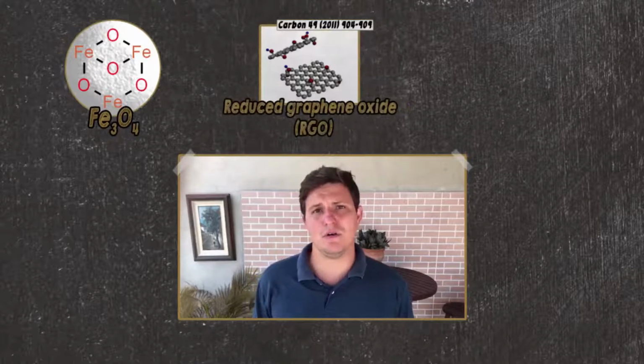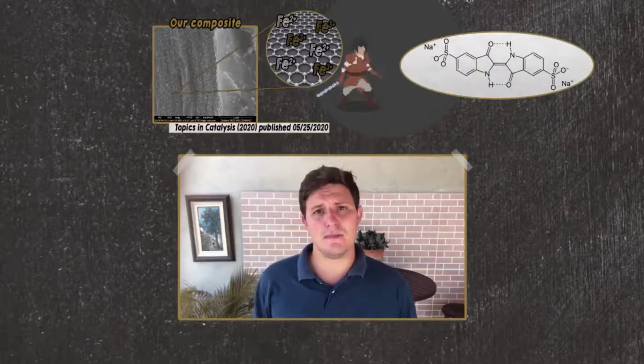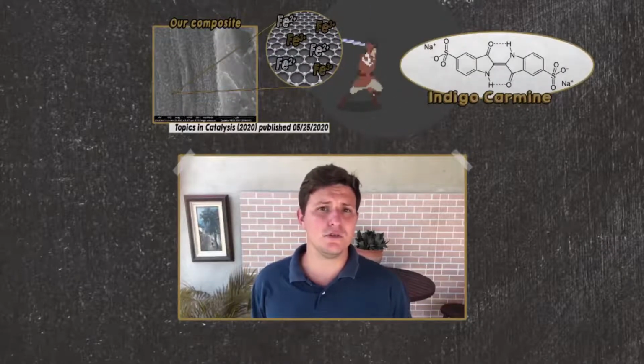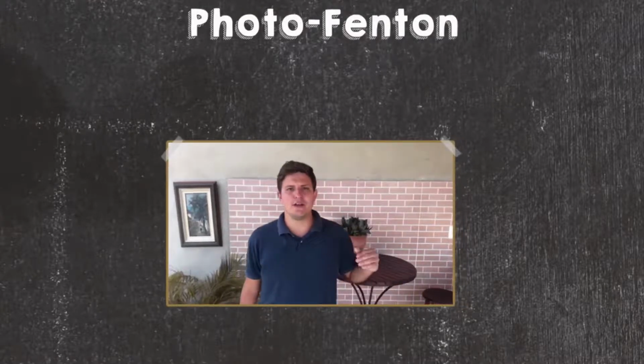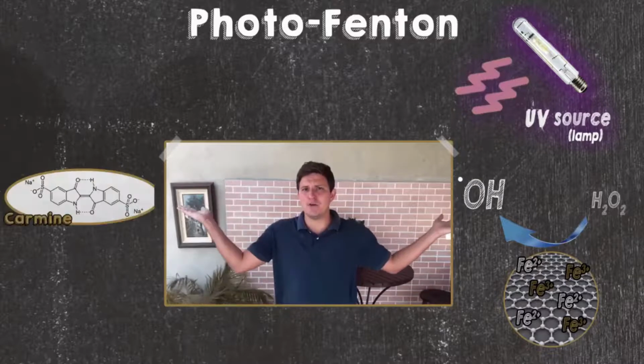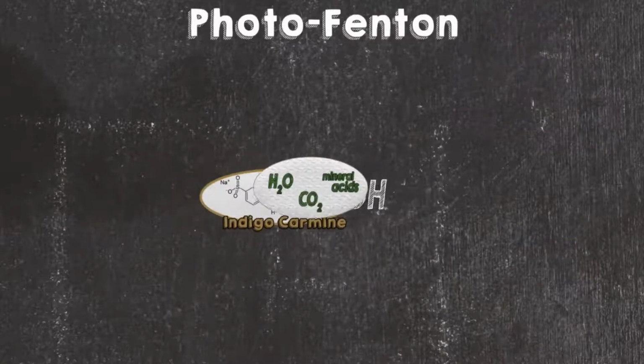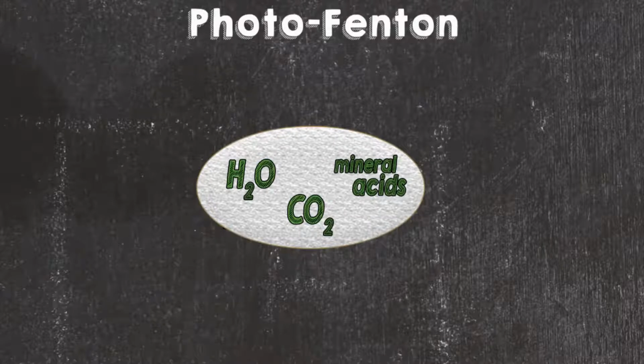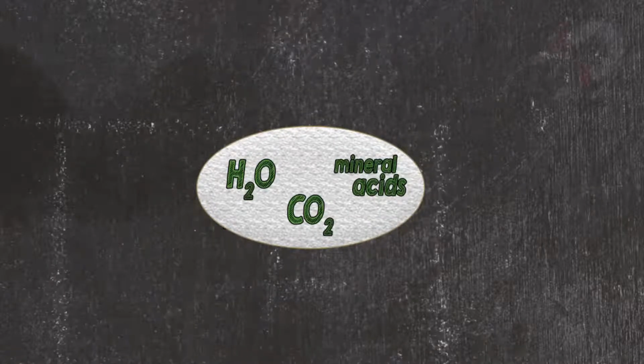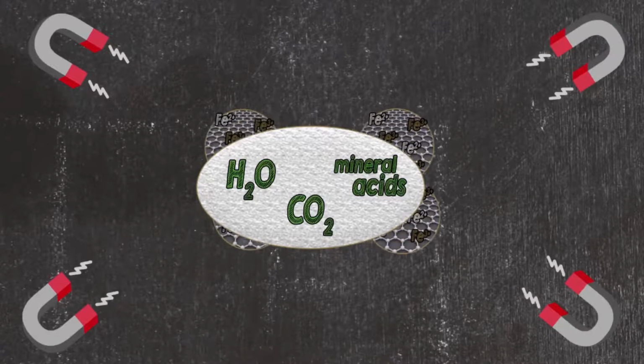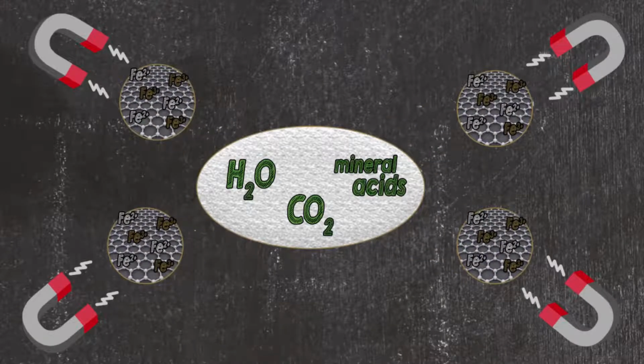That said, the objective in this work was to synthesize magnetic iron oxide particles anchored on RGO sheets, turning this composite material to discolorate indigo carmine dye solution, which is a widely used organic dye in the world. This is possible due to a process known as photo-Fenton process, which generates hydroxyl radicals to attack the indigo carmine dye molecule, producing water, CO2, and mineral acids. It is much better for the environment, isn't it? And after all this happened, we can still easily recover the catalyst by approximating a magnet.